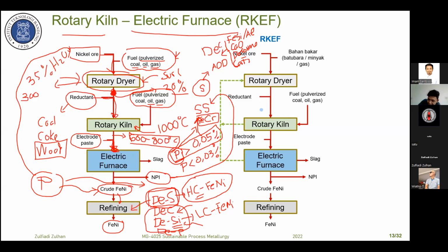desulfurization. We have observed that in some stainless steel making plants the sulfur content of around 0.1% can be removed to less than 0.01% at the end of the AOD converter. So phosphor is really very strict if we produce NPI or high carbon ferronickel. If we produce low carbon ferronickel, the phosphor can be reduced during oxygen blowing in a converter, for example.